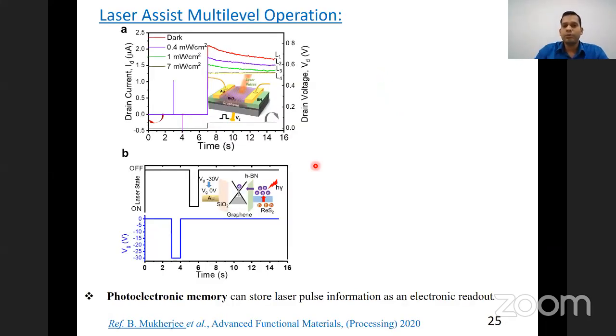So we are interested in laser-assisted multi-level operation. Later on, we analyzed this device with light assistance, because this rhenium disulfide is a very strong material for optoelectronics. Here we use both a gate pulse and a laser pulse, and we synchronize them, such that the drain current will follow these two conditions. And finally, we can have 4 different erase states, depending on the laser intensity we use. So we can have here L1 to L4, as I showed, 4 different states.